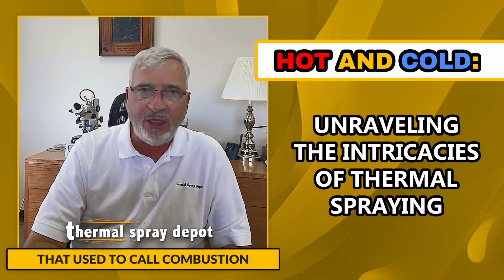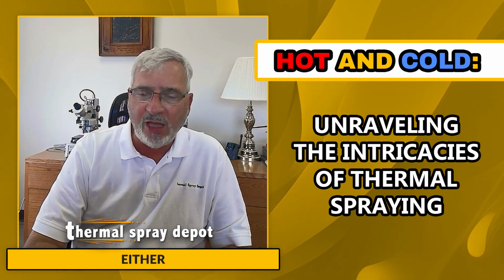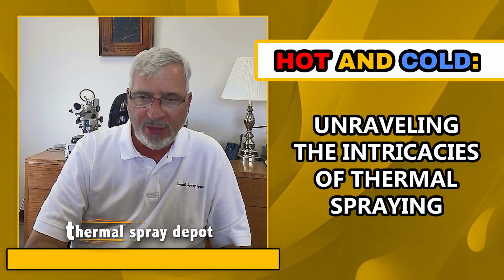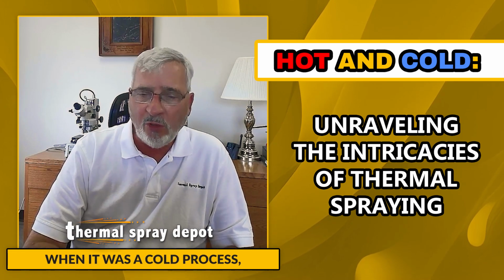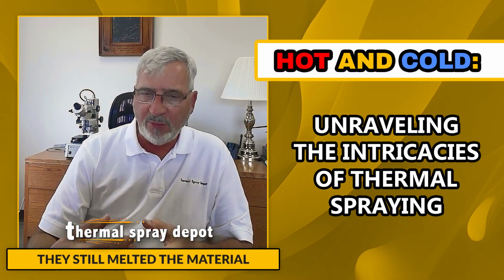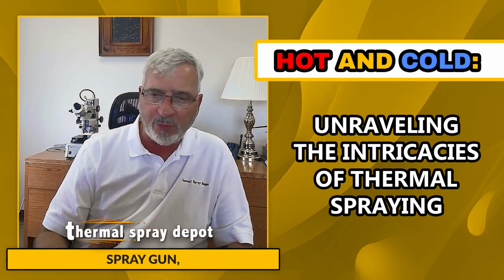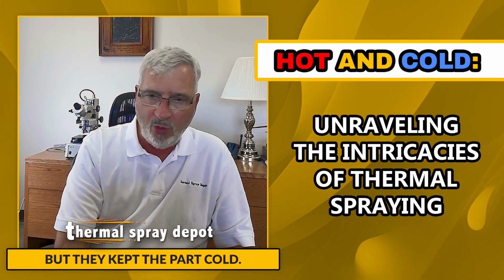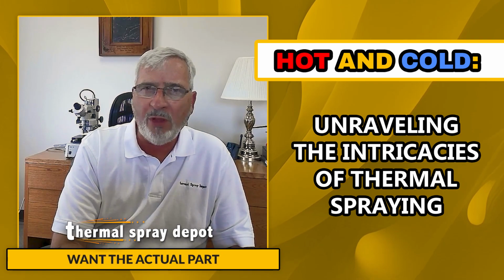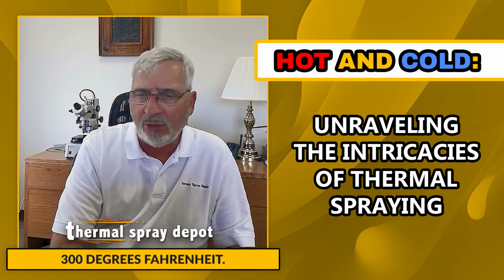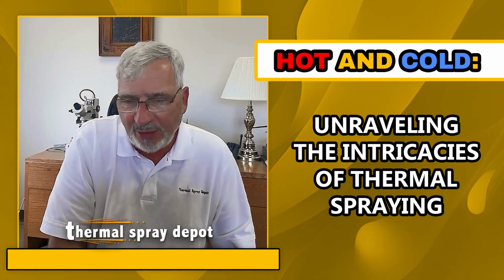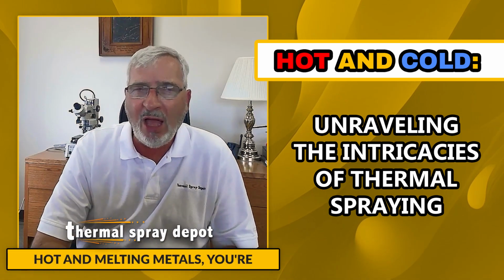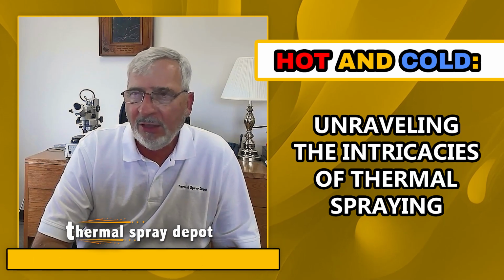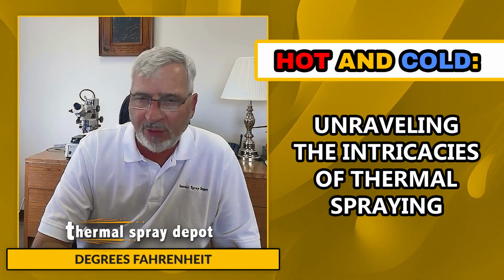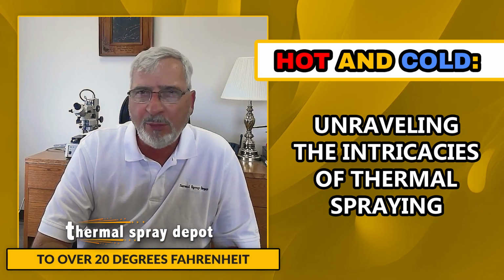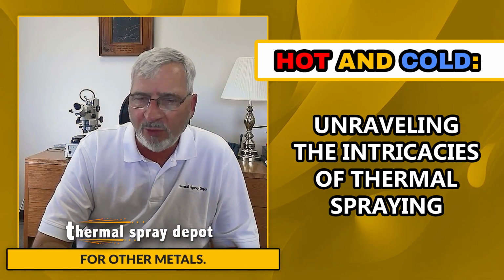There's one company that used to call the combustion powder process either a cold process or a hot process. What they meant was, when it was a cold process, they still melted the material that you were running through the thermal spray gun, but they kept the part cold. So when I say cold, they didn't want the actual part that you were spraying to exceed 300 degrees Fahrenheit. That's hot to people, but when we're talking about melting metals, you're starting probably in the 1200 degrees Fahrenheit range for things like aluminum and zinc, up to over 2000 degrees Fahrenheit for other metals.